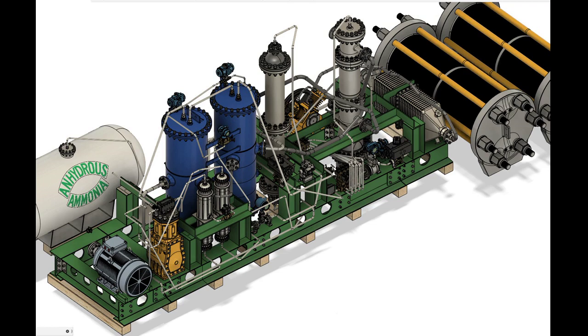A large-scale ammonia converter has a diameter of up to 3 meters. This size reactor has a surface-to-volume ratio of roughly 1.72. The miniature reactor has a surface-to-volume ratio of 35, or roughly 20x higher, while the volume of the reactor is 5,500x larger. For the large-scale reactor with 50 cubic meters of catalyst volume, the total thermal budget is 113,000 kilowatt-hours. The heat flux through the reactor wall is 9,800 kilowatt-hours without any insulation. This corresponds to 8% of the hourly heat flux, or 24 times greater than our insulated microreactor.